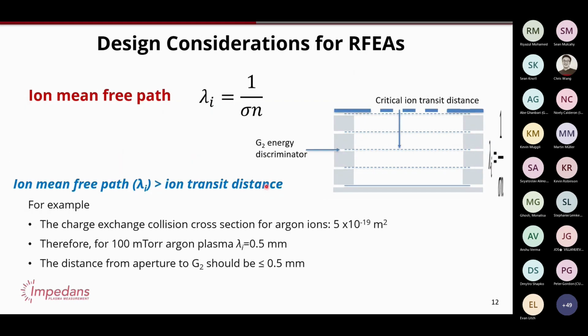What else must you consider? In order to measure what an ion energy really is when it hits your substrate, you can imagine the top plate of this is representing your substrate, and then you're going inside the sensor. The ion must be able to go from the plasma through the sensor, through the discrimination grid, without having any collisions. Because if there's any collisions, you distort the ion energy measurement. So that means that these sensors have to be very, very thin. Because if they're too big, a particle will collide as it's passing through here.